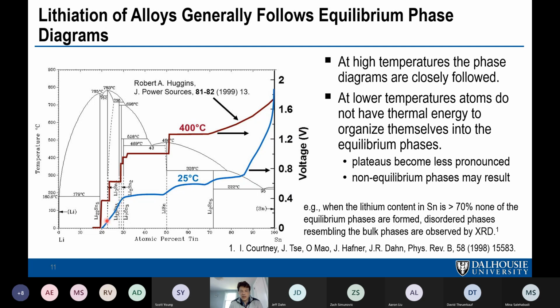You don't get these phases anymore in the phase diagram. And there's two reasons for this. One reason is these things have very large unit cells. So at room temperature, it's hard for these materials to organize themselves in these complicated structures. The atoms aren't moving around as easily as at 400 degrees Celsius. Plus, you'll notice here, this is a region where you have high melting point. And a high melting point means strong bonds. And again, in order to move elements around with strong bonds at room temperature, that's going to be very difficult.